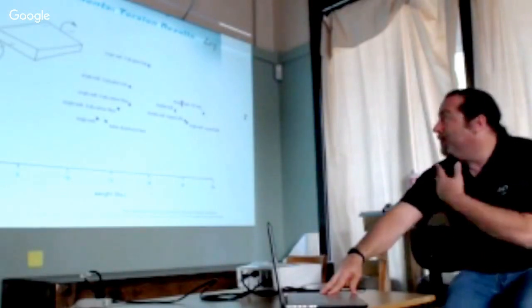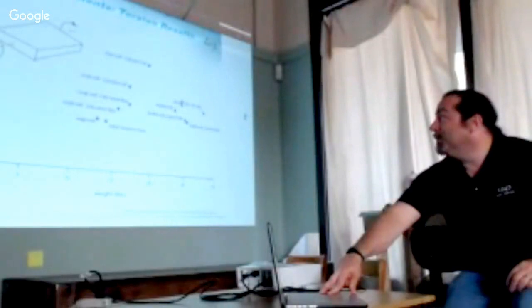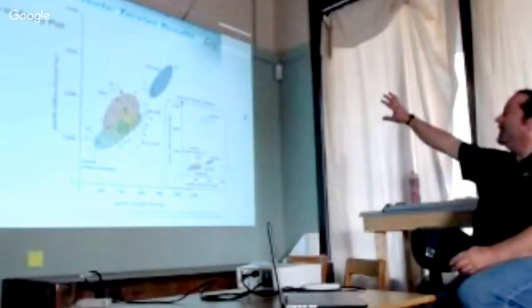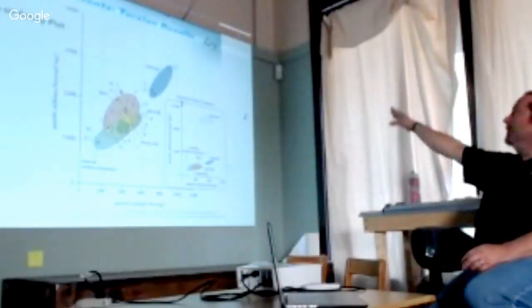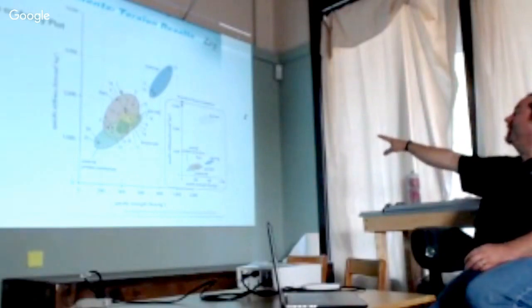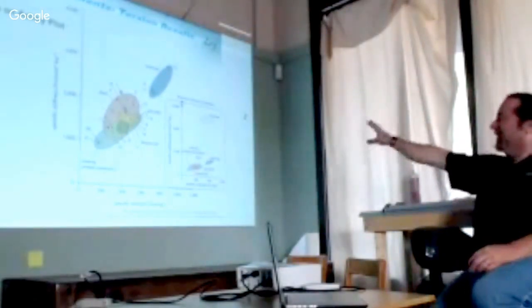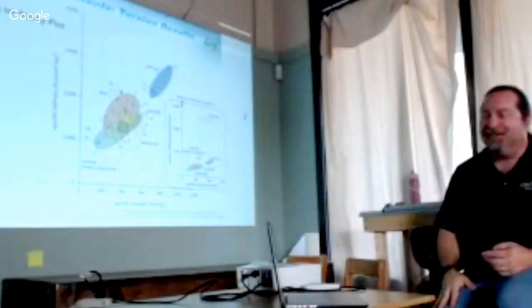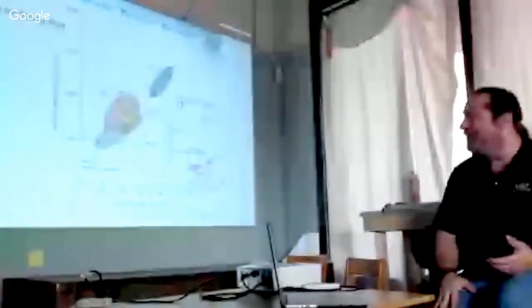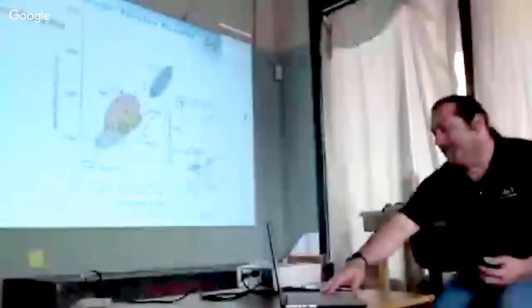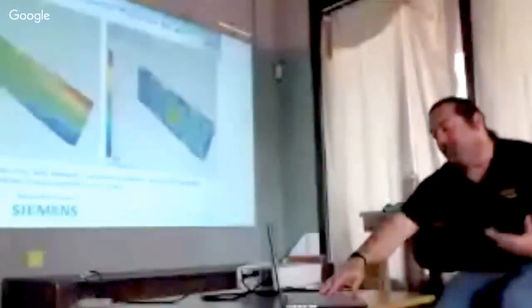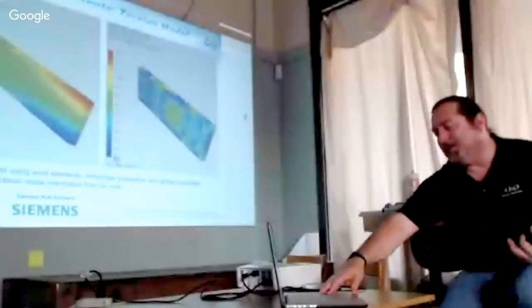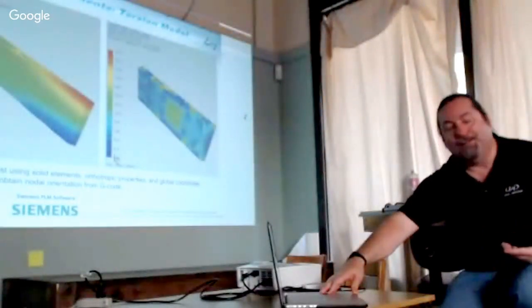These are just the results in torsion for some of the boxes, and then here's the Ashby chart in torsion. And here the overwrap did really well, as long as you take aluminum off. Aluminum also did really well. This little inset shows where the aluminum was. So it was interesting to see that. We're just starting to do some simulations. We got our hands on some.